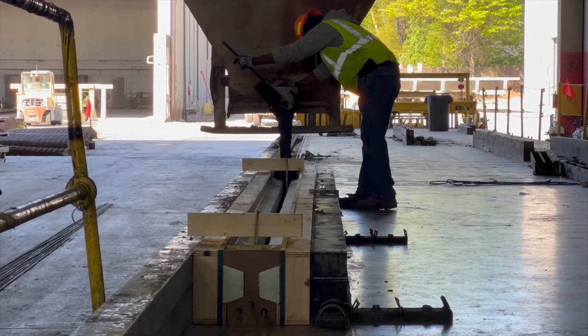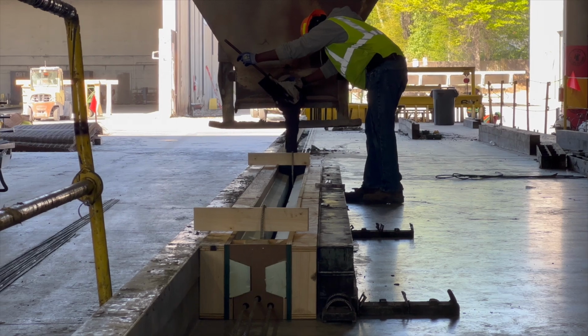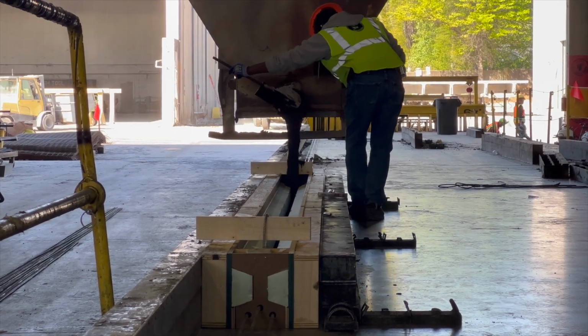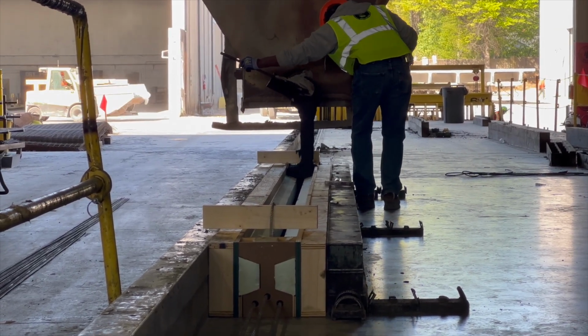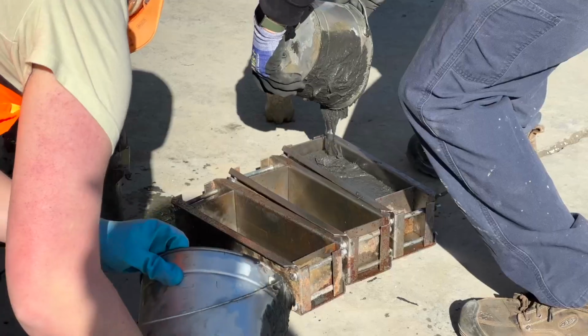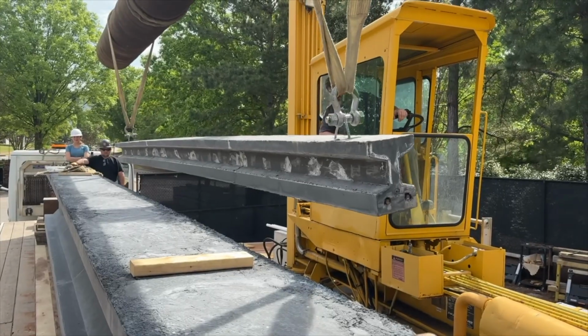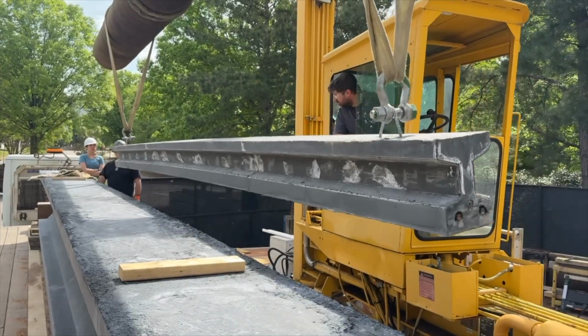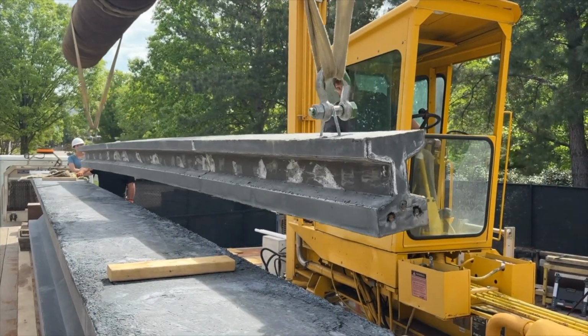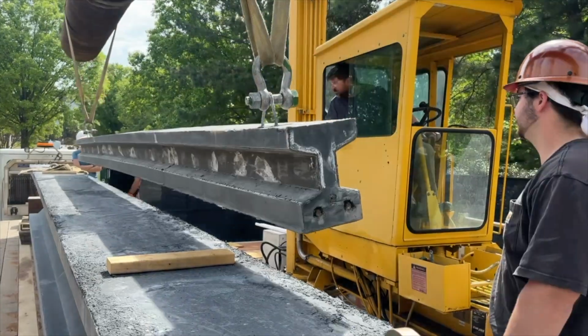Once we had our mix, we went over to our Big Beam's little form and started pouring the concrete in. We also made sure we had enough cylinders and rectangular prisms for our prism tests. We then had our beam show up on the truck. That's our lab zone Dr. Lucier driving the MyJack you see there.